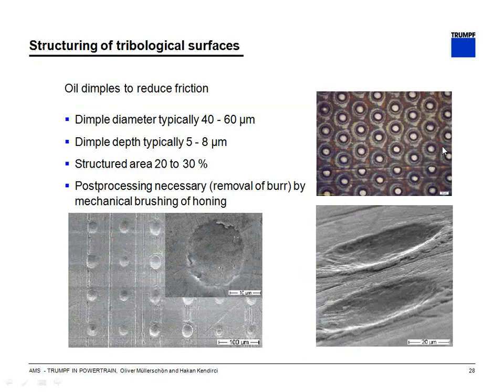But we also can use this short pulsed laser for changing or adapting the tribological properties of materials. Here with this example you can see some oil dimples made with such a short pulsed laser. Typical diameter for such a little oil dimple is about 40 to 60 microns. The depth of it is about 5 to 8 microns, a very small one.